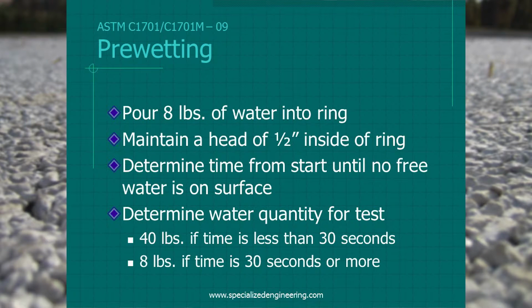So this is a 2-part test. The first part is called a pre-wetting test, where we'll weigh out 8 pounds of water, and then we'll pour the water into the ring, inside the ring, into the pervious concrete. And we maintain a head of 1/2 inch. You'll see when that's passed around, on the bottom of it, there's two lines grooved in and marked in, and that's your 1/2 inch plus or minus range to keep that water level. So you keep a constant head of water.